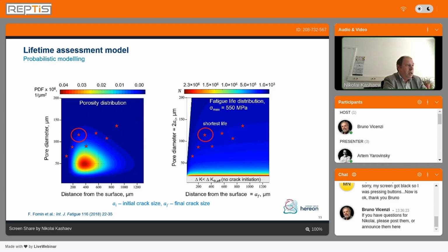And in principle, if we consider that all pores have to result in a number of cycles of at least 10 to the power 5, we can move this curve and consider that all pores have to be located under these curves. And this is in principle the area under this curve. It's the probability of failure, and the probability of failure we can then easily calculate using this analysis.